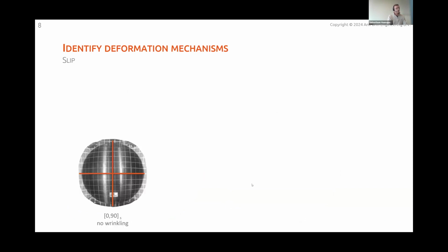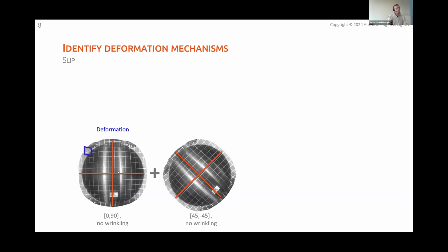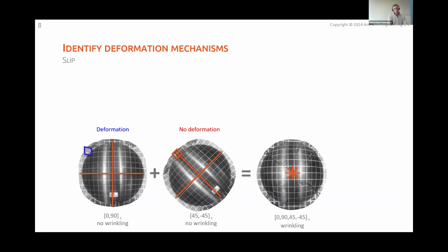The last deformation mechanism is about slip. So you may remember the first result with the cross-ply layup we had. It looked like this, a nice dome without so much wrinkling. And we saw a lot of shear deformation at specific spots. Suppose we have the same cross-ply laminate, but we rotate it by 45 degrees, then we get a rotated deformation field, where at this point we have now no deformation, whereas we had deformation in the original rotation. So for a quasi-isotropic layup, actually both situations are present, but superimposed. And that gave us this result, a lot of big wrinkles.